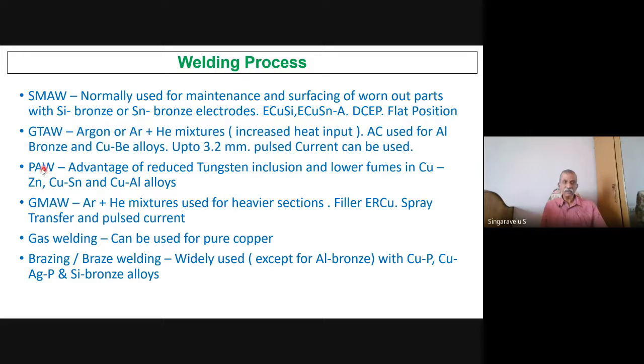Plasma arc welding can be done. The advantage is reduced tungsten inclusion and lower fumes. Why? The tungsten rod is kept inside the, what do you call it, the cup, the nozzle. It is not protruding outside. In TIG, it is protruding outside. In plasma arc welding, it is kept well inside, recessed inside. No inclusion, very good process.